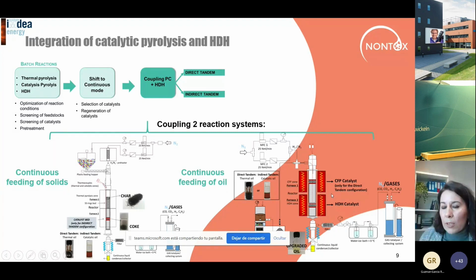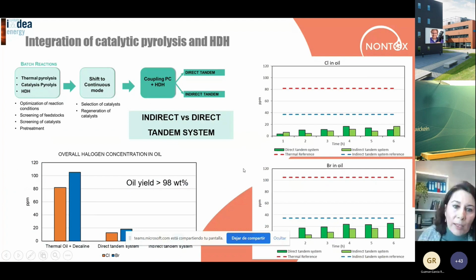The direct configuration is a bit different. In the first reaction, there is no catalyst, just thermal degradation, and then on the right, we place the two catalysts. In the up part, there is the catalytic pyrolysis catalyst, and on the down part is the HDH catalyst. The results were quite good in both cases, but we can say that in the case of the indirect configuration, which is the light green color, it is a bit better in terms of the halogen contents, which are very low, below, again, 10 ppm in many cases, and with higher stability.